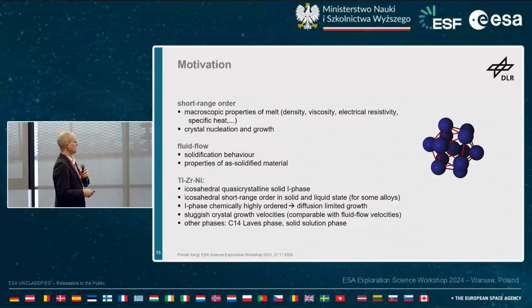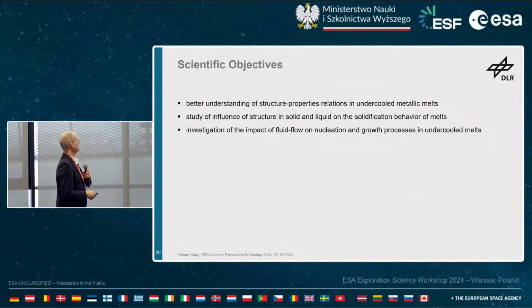The system itself has an icosahedral short-range order in the liquid state as in the solid state for some alloy compositions. This icosahedral phase is chemically highly ordered, so it asks for diffusion limited growth, and you have sluggish crystal growth velocities that are comparable with the fluid flow velocities. So what the scientific objectives are is a better understanding of structure-property relations in undercooled metallic melts, the study of the influence of structure in the solid and liquid on the solidification behavior, and an investigation of the impact on fluid flow and nucleation and growth processes in undercooled melts.